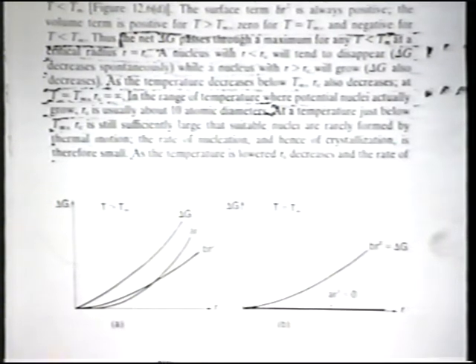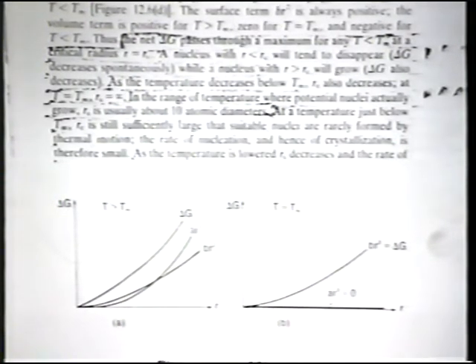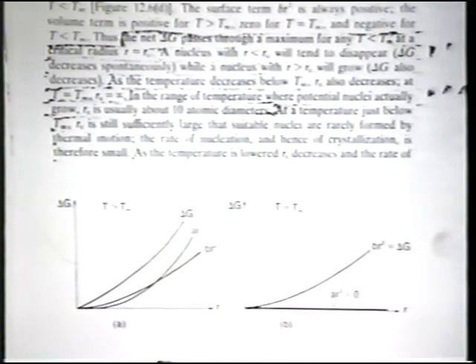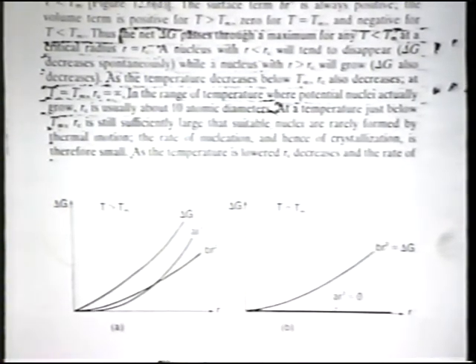So here's a reference for it right here in a published text. If you have 10 atomic diameters or larger, it will aggregate to itself and grow metal. If the atoms are in 10 atomic diameters or less, they repulse each other. They will not come together, and you don't get metal. Now that's just a general number, the 10. In fact, for iridium, for instance, it's 9 atom clusters. Anything larger than 9 grows. Anything less than 9 comes apart.